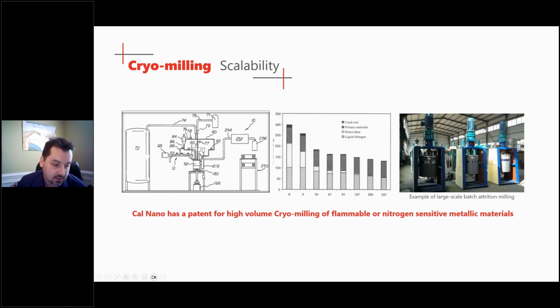In some cases, I mentioned how the materials are usually in a liquid nitrogen slurry. That's true, except for in the cases where the material likes nitrogen. Typically, it's inert and doesn't react with too much, but some materials like nitrogen. And just from a material property perspective, we need to mill in liquid argon. Argon being substantially more rare and thus more expensive, that becomes cost prohibitive. We have a system that can mill in liquid argon at the economics closer to that of liquid nitrogen, while also mitigating the dangers associated with producing the fine grain, fine particle sizes of metals.